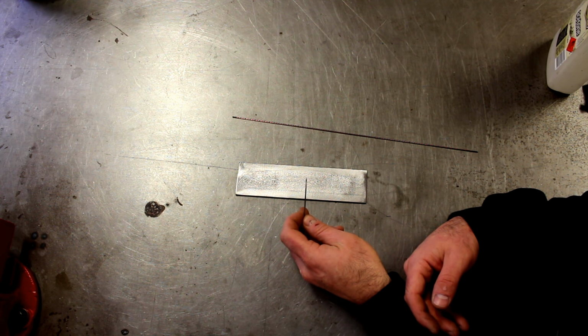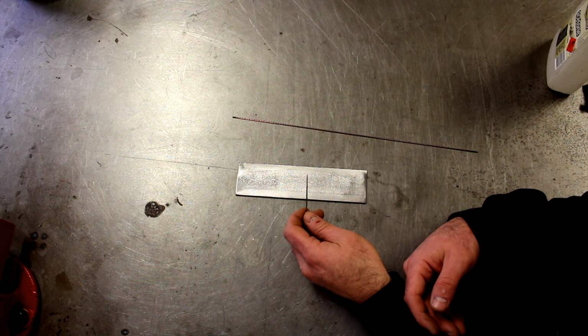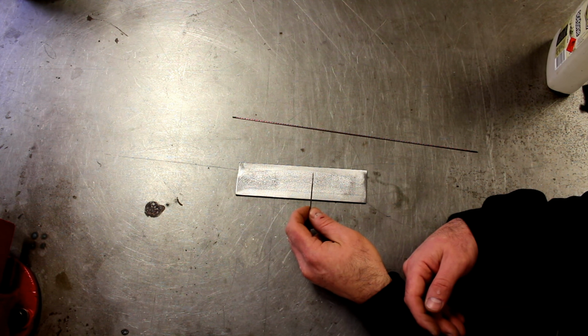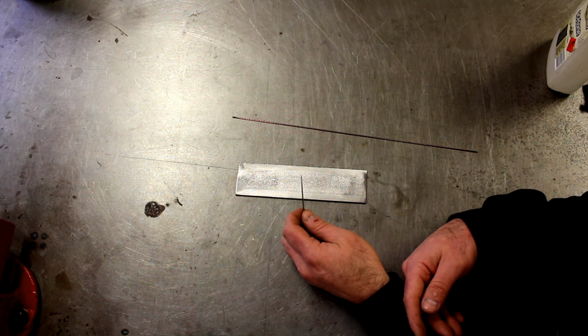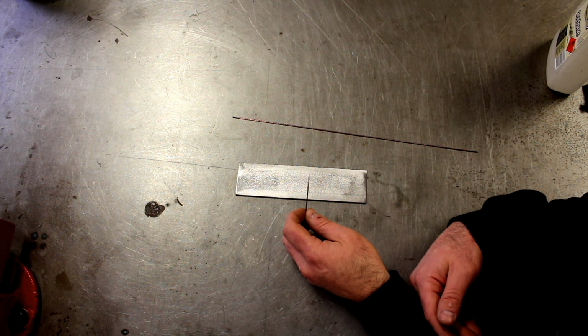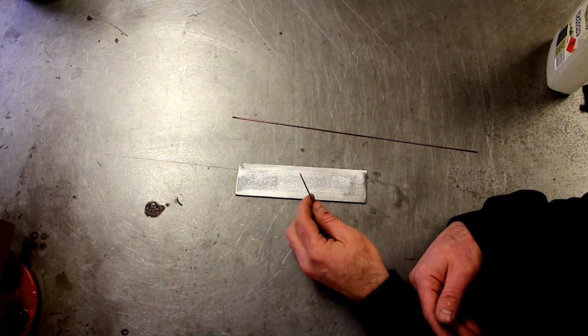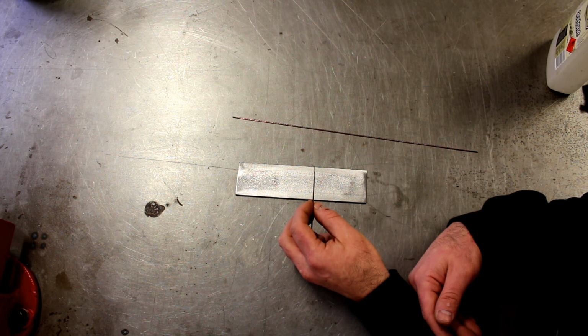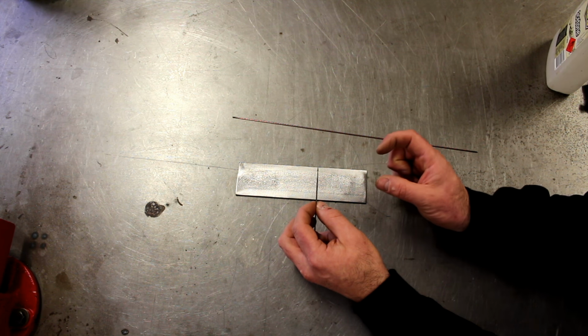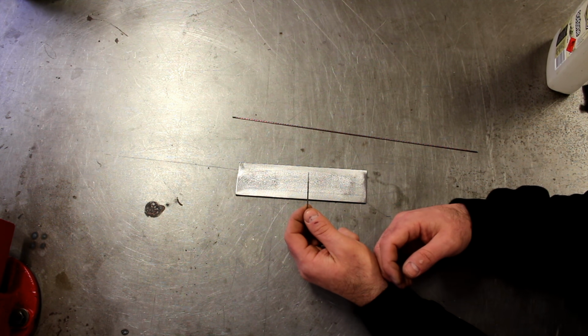Now I didn't use my bench grinder wheel for this job because bench grinder wheels tend to pick up metal, and then they can embed that back into your tungsten electrode, and you'll be wondering why you've got shitty welds. So either use a dedicated wheel in a bench grinder for grinding tungstens, or like I do, use a belt sander to sharpen them. Now on a steel job like this, you just sharpen them to a point, and the length of that point should be 2 to 3 diameters, roughly. So just sharpen it to a point, and if it's nice and clean like that, we're all good.